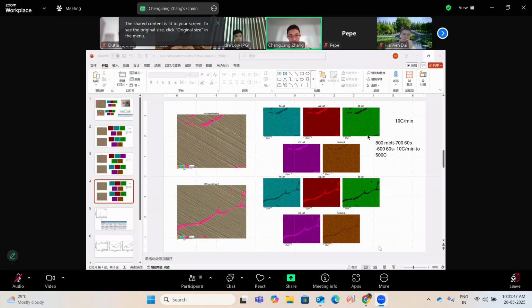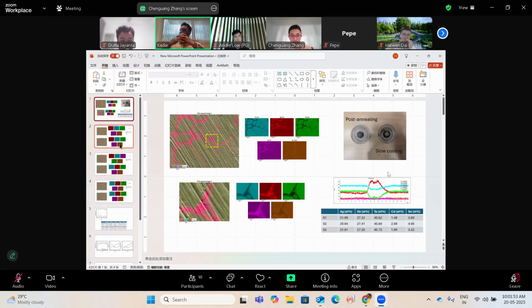In the last 2 weeks, let me provide a quick introduction before the thinking: what the material is and what the thinking process is. In the material, we use the 4% cadmium telluride doped and 10% selenide doped, co-doped silver antimony telluride that we previously published. And actually, we do two different experiments. The first one is that we did the post-annealing at 200 Celsius for 24 hours. And the other one, Delvin and I were working together to control the cooling rate from the melting state to room temperature.